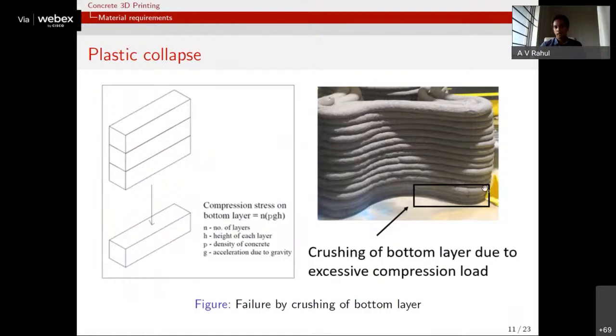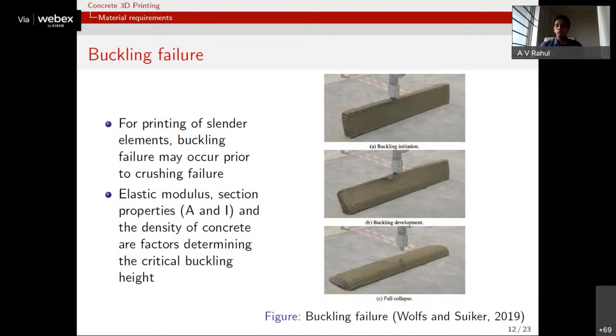The bottom layer starts to flow, and there's plastic collapse occurring in the material. Buckling type of collapse occurs in the case of thin elements. If you have very thin elements, then it can undergo lateral deformations due to buckling, and then the element can undergo a buckling failure.